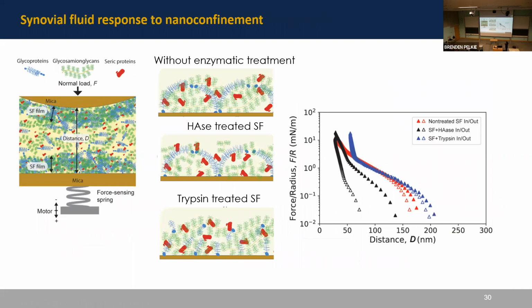And we can also measure the nanomechanics of the synovial fluid by using the SFA, and we want to compare the role of the different components of synovial fluid. So we compared the fully formed synovial fluid layer with hyaluronidase treated synovial fluid to cleave the hyaluronic acid, and trypsin treated synovial fluid to cleave the glycoproteins, such as lubricin. And the force curve, a typical representative curve, is shown here.